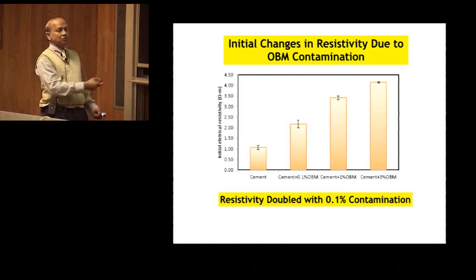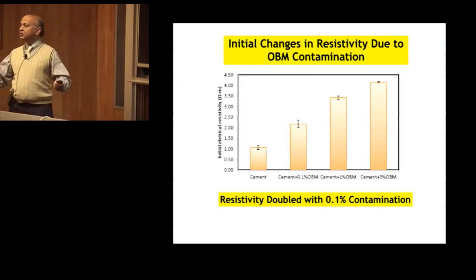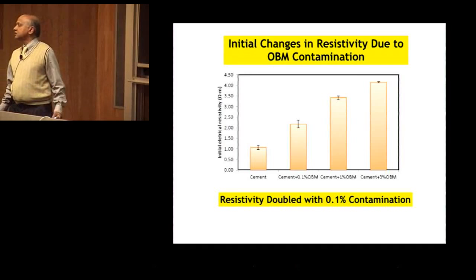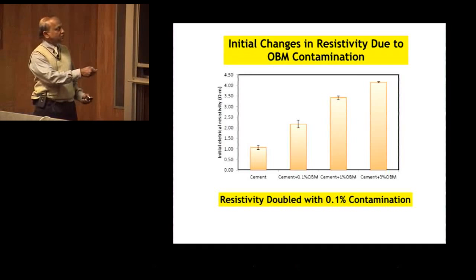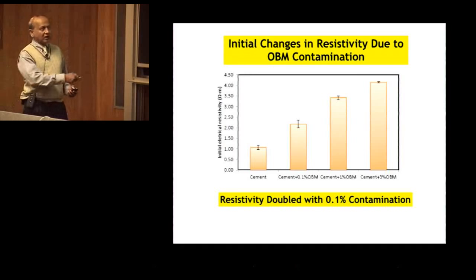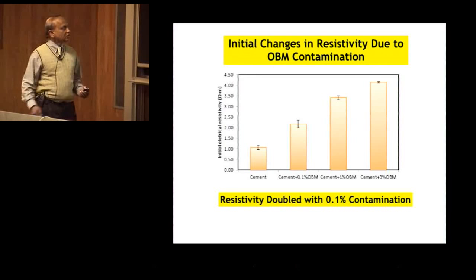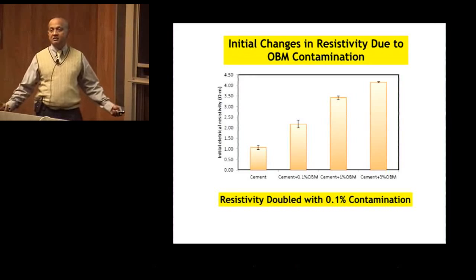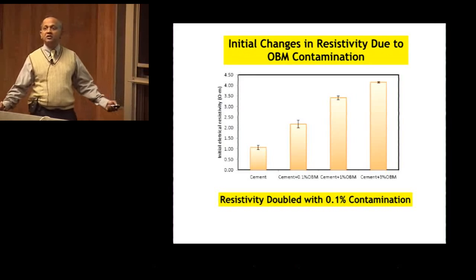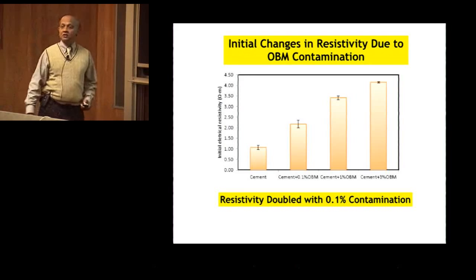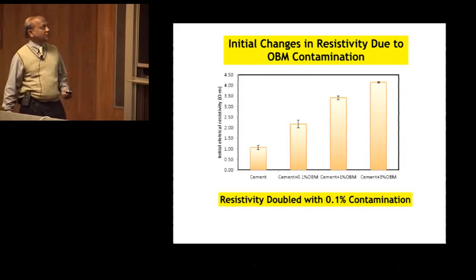So monitoring the resistivity will tell you that your cement is getting contaminated. And you can see, just to show you the contamination, how the resistivity doubled with a small amount of contamination. Now, we don't have these things to detect. We don't know whether your cement is contaminated or not. But with this new technology, yes, we can detect that.